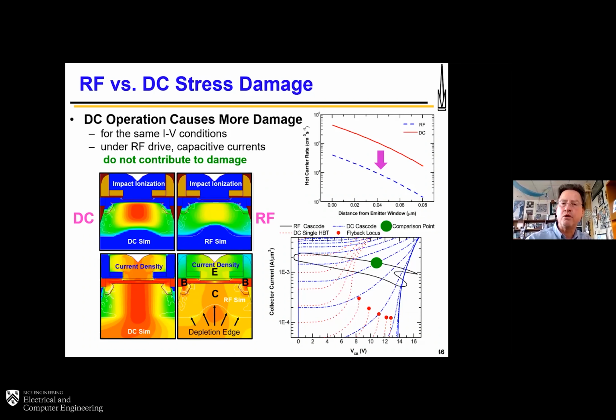But if you look on the upper right, the hot carrier generation rate is about an order of magnitude lower in the RF sense. And that translates into far improved reliability for the circuit than it did for the device. Now, the problem is that most of industry specifies their SOA and reliability from DC measurements. And so it's very clear then that those are generally very over-conservative with respect to what one can get away with, and hence they're throwing away performance that can be done reliably.